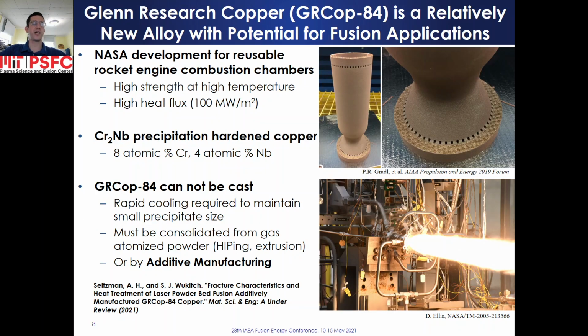Glenn Research Copper 84, or GRCop-84, is a relatively new alloy with high potential for fusion applications. Originally developed in collaboration with NASA for reusable rocket engine combustion chambers, GRCop-84 maintains high strength at high temperatures, while maintaining good electrical and thermal conductivity to withstand high heat fluxes exceeding 100 megawatts per square meter. Niobium chromide, comprising 8 atomic percent chromium and 4 atomic percent niobium in the alloy, forms in small precipitates during rapid cooling of a gas atomized powder. Casting is not possible due to the precipitate growth during a slow cooling process. Hot isostatic pressing or extrusion may be used for consolidation of GRCop-84 powder. However, the greatest mechanical properties are achieved during an additive manufacturing process.